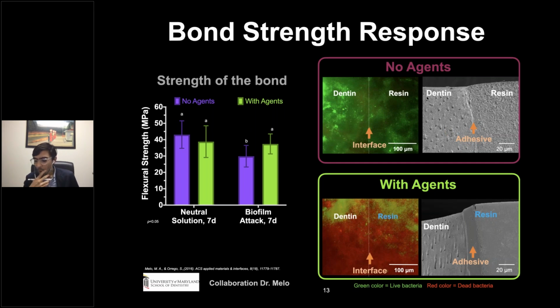Now, if you look in the microscope, we see that interface: dentin, adhesive, and resin. In the resin and adhesive side, there is no clear distinction where is the resin and where is the adhesive. You visually see an increased amount of surface roughness, which tells us indirectly that the biofilm is doing something to those surfaces.